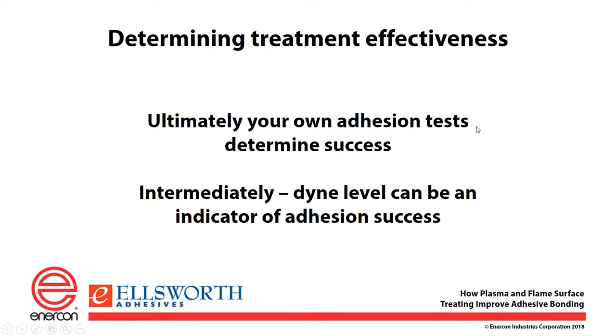So how do you determine the treatment effectiveness? Well, I mentioned that Dyne and contact angle are good indicators of adhesion, but they're not perfect. We need to run the test. So we generally have a 2-step system when we're looking at application. The one is proof of concept. Does it work? Can we increase your surface energy with whichever method we choose in order to improve your process and get you the results that you're looking for? The second part of that is dialing it in to meet your specific needs.